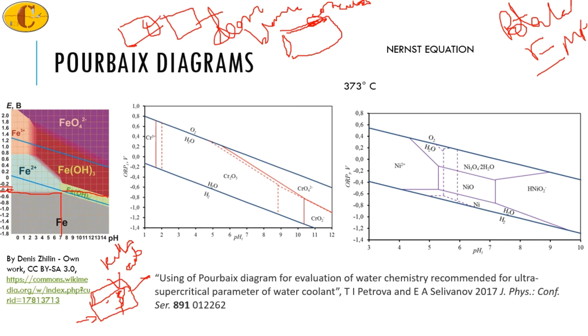Now, if instead of carbon steel you decide to use stainless steel, then the stainless steel will basically have a chromium oxide film on the top. These two are the Pourbaix diagrams for chromium and nickel, but they are at a very high temperature. So let us only focus on the compounds that are shown over here. In this case, when you have a stainless steel, you have a chromium oxide film on the top. So obviously the stainless steel will not have -0.4 V, it will have something more positive, let's say -0.2 V, because the chromium oxide film will protect it from corrosion.